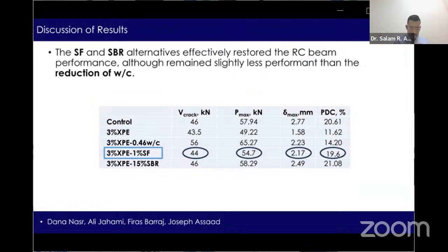Alternatively, the steel fiber or SBR alternatives also proved to be efficient to restore the reinforced concrete beam's performance, but these remain slightly less performant than the water to cement ratio reduction alternative. For example, when 1% steel fiber was used in the concrete mix, the values of the shear strength properties reached V crack 44 kilonewton, Pmax 54.7 kilonewton, delta max 2.17 millimeters, and PDC index 19.6%.